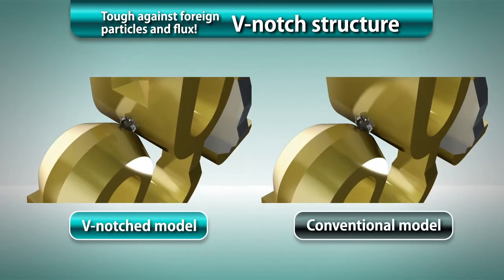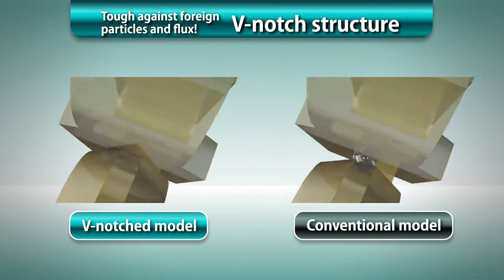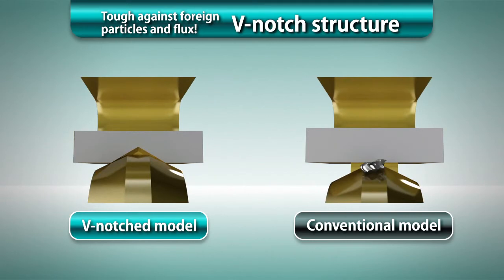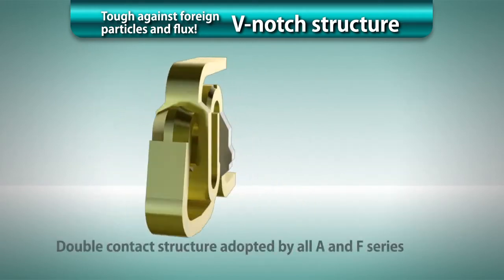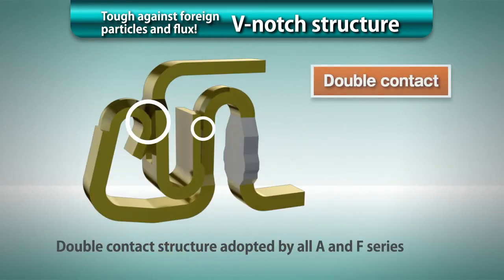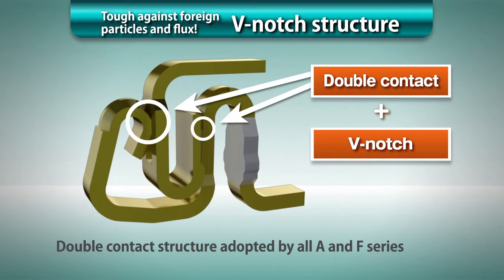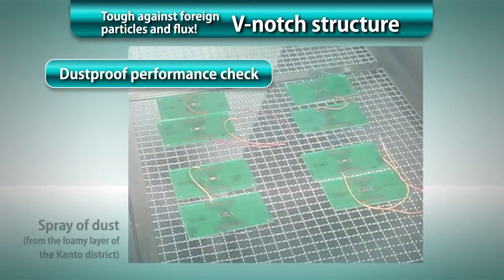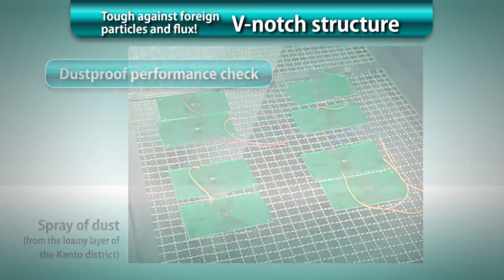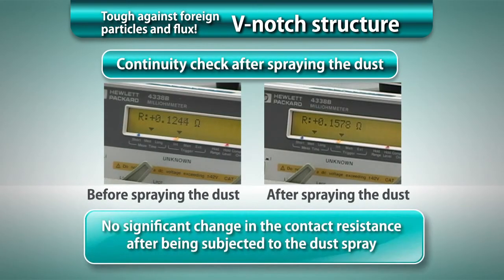In combination with a structure that shifts the contact positions during the connection process, the V-notch structure has achieved high resistance to entry of dust, dispersed flux, or other foreign particles of a level that cannot exist under actual environmental conditions of use. In addition, the double contact structure securely holds the header for further improvement of the contact reliability. The V-notch and double contact structures generate synergetic effects, allowing for significant enhancement of the contact reliability. As you can see, the contact resistance showed no significant change after the dust spray.